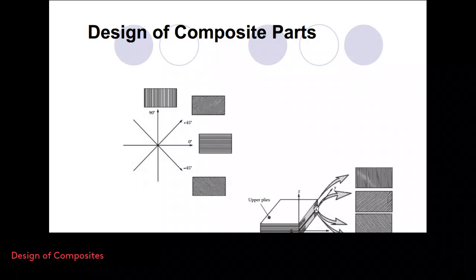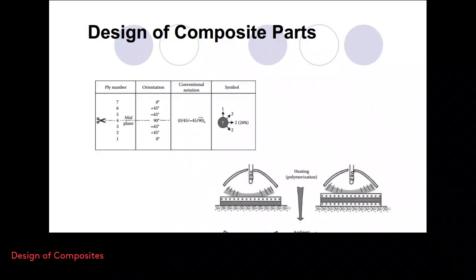In fact, we generally want to use symmetric configurations, and due to the coupling between the shear stresses and the normal shear strains and normal stresses, which causes warping and twisting, we prefer to use off-axis oriented plies close to the center of the laminate, and the others towards the upper surface or bottom surface of the laminate. So you can use either 90-degree oriented ply at the top or 0-degree oriented ply at the top, depending on your design and on the number of the plies and configuration or properties that you want to attain.